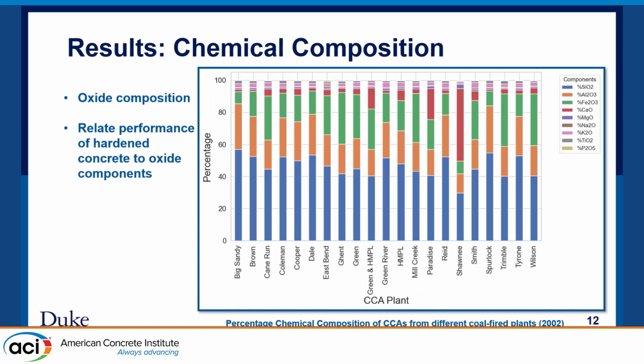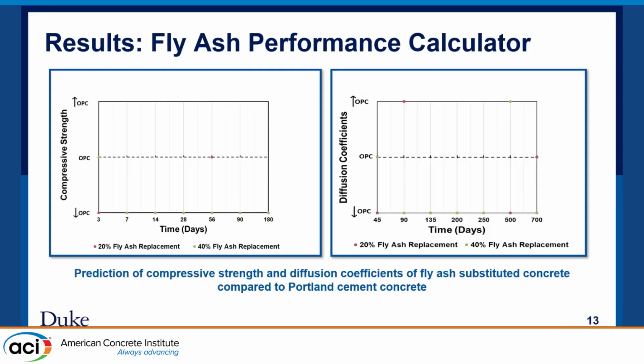For the results we have, this is the presentation of the chemical composition in certain coal combustion ash for the year 2002. These are the results for different plants all around the US. And this is the result from the fly ash performance calculator. We can see that for some percentages of fly ash in the concrete, it shows better results than OPC. But for some, it doesn't predict better performance than OPC.